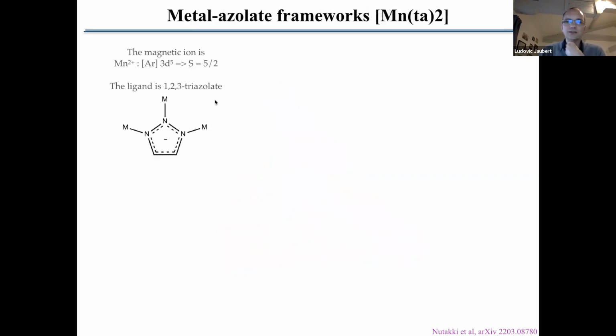And so how to do that? You can do that with chemistry and with metal organics, metal azolates actually. So what we did is that we considered a manganese-based material. So why manganese? Because manganese is a 3d5 magnetic ion, and 3d5 means that half of the 3d band is filled. And a half-filled band means that you have a large magnetic moment, so 5/2. That's very classical, so you can consider classical spins. And on top of that, because it's half filled, that's quite an isotropic system. So you do not expect to have strong anisotropy here. To a first approximation, you can really assume isotropic classical spins for the manganese Mn2+ magnetic ion.